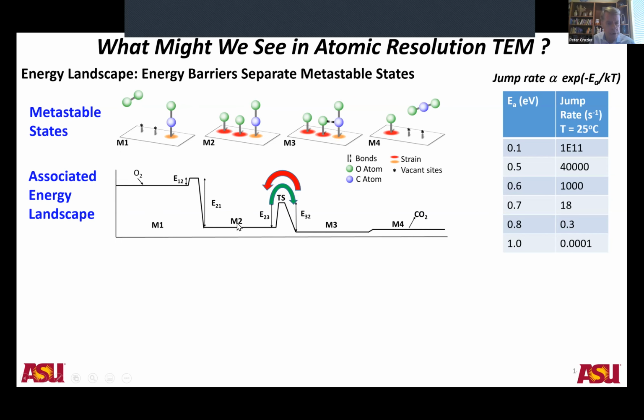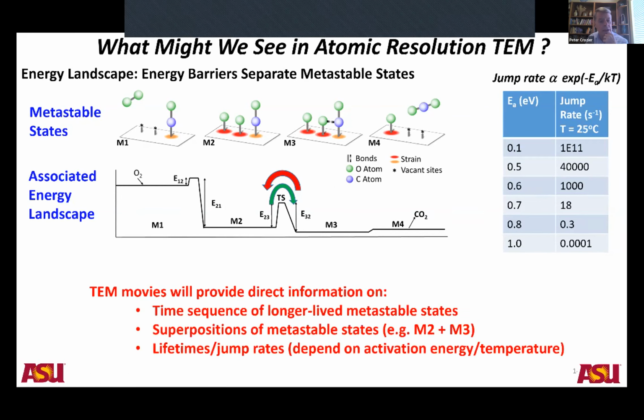And the energy landscape, of course, these metastable states are separated from each other by activation energies. And if you look at typical values of activation energies and you look at typical jump rates here, what you see is that, for example, if you have an activation energy of about 0.6 eV, at room temperature, the fastest jump rate would be 1,000 jumps per second. If you go to 0.7 eV, we're down to 18 jumps per second. So actually, these activation energy barriers are going to slow down the transition between different metastable states. And so if you think about what you might see in an electron microscope, you're going to see time sequences between the longer-lived metastable states.